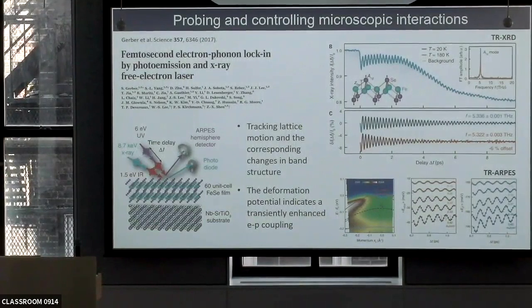And if we wanted to see what happens to the superconducting gap at the zone boundary, you would need a much more energetic photon to do that, which is usually not available, but is becoming available with our source in our lab. So that would be an interesting experiment we would of course like to do while looking at the zone boundary.